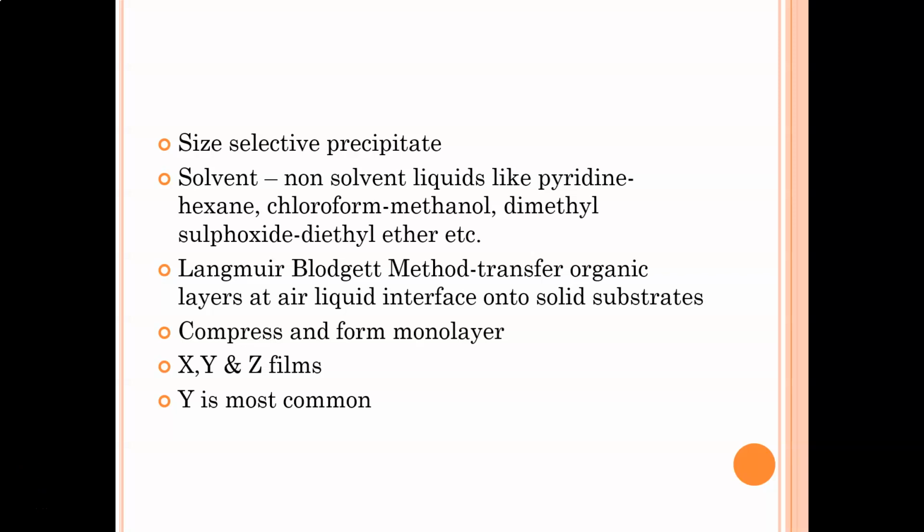When nanomaterials are synthesized, they are synthesized in different size ranges. But you may want to have a uniform size range. You may want to separate particles of similar size ranges together, for which it's very important to make a proper choice of a pair of a solvent and a non-solvent liquid, like pyridine-hexane, chloroform-methanol, dimethyl sulfoxide and diethyl ether.